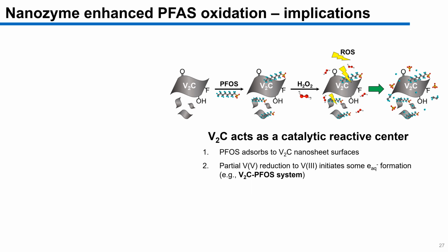And then when you have just vanadium carbide and PFAS now at the surface of the vanadium carbide, we think this electron transfer process must be occurring to some degree because we observe a solvated electron formation in the absence of hydrogen peroxide. And we did see that trifluoroacetic acid byproduct formation in this system. So there must be some electron transfer, some shuttling occurring in that system in the absence of hydrogen peroxide.